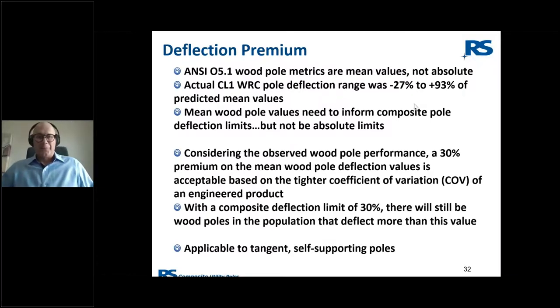Now, I'm going to do my best not to read directly here, but there's a lot of information to unpack. So the ANSI O5.1 wood pole metrics are mean performance values and not absolute. The actual class one Western red cedar deflection performance range that we observed in testing was minus 27 up to plus 93% of predicted mean values. As a result of this, we know that mean wood pole values need to inform composite pole deflection limits, but not in fact be absolute limits. Considering the observed wood pole performance, a 30% deflection premium on the mean wood pole deflection value is acceptable based on the tighter coefficient of variation, or COV, of an engineered product.